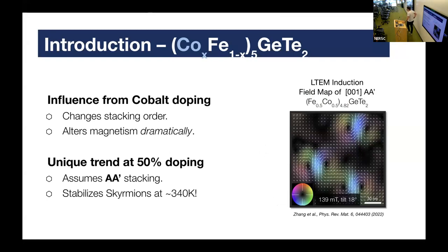And then to the point I was making earlier with the AA prime stacking here, in our collaboration here at UC Berkeley. This image we're seeing is an LTEM image, which is Lorentz transmission electron microscopy image, showing the magnetic field on the surface of this material. And so those very beautiful rainbow surface circular vortices are actually the signatures that are showing that we're getting these really interesting spin helical structures on the surface of this material. And what's even more exciting and hasn't been discovered in many materials is the fact that these skyrmion structures, these really interesting spin vortices actually remain stable up into room temperature. And so there's these hopes that these magnetic quasi particles, what skyrmions are, would be able to serve as some sort of information bit if we're trying to develop the field of skyrmionics.